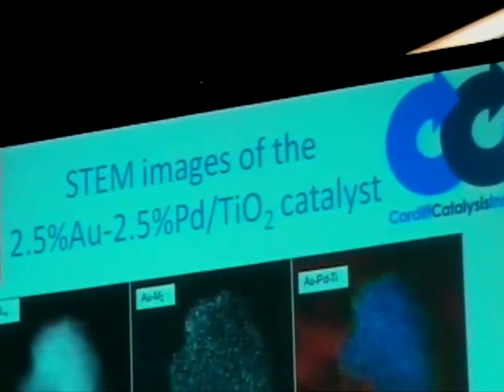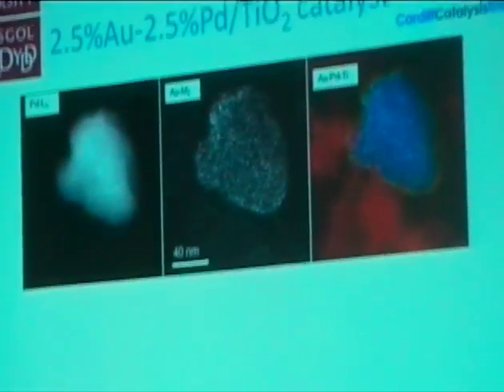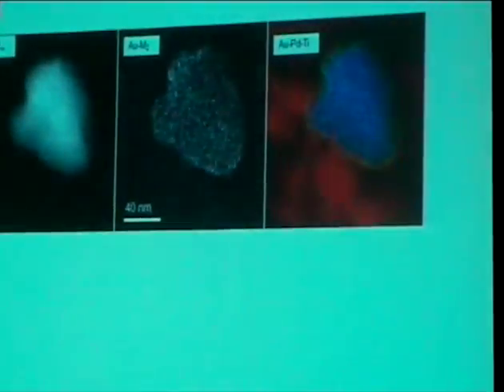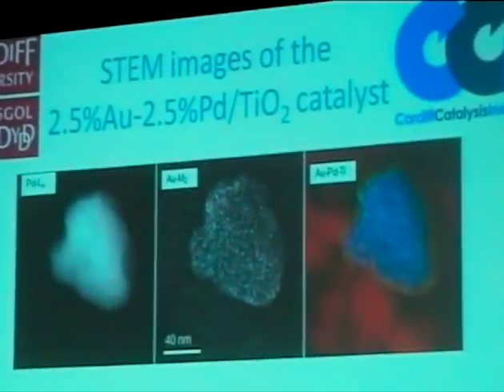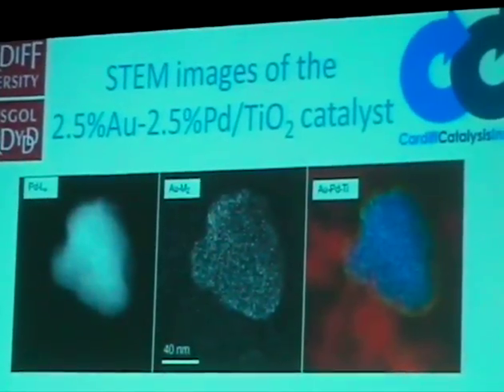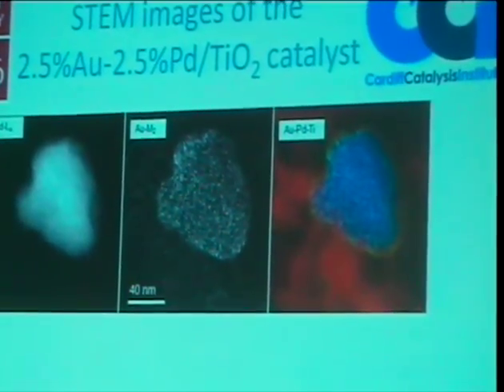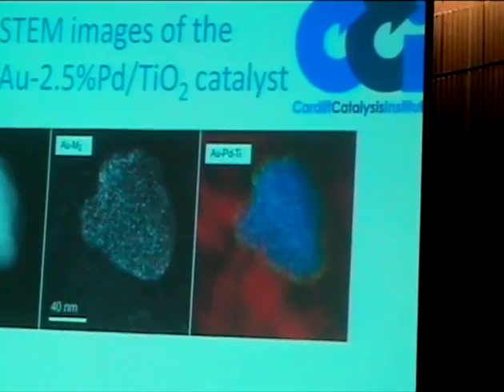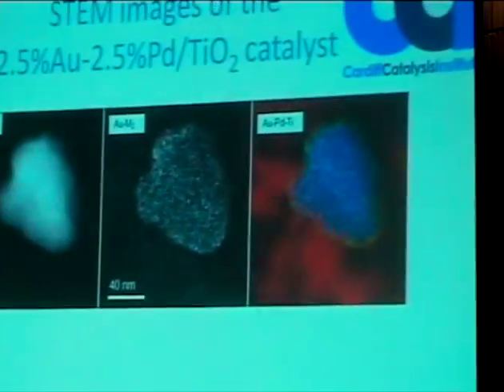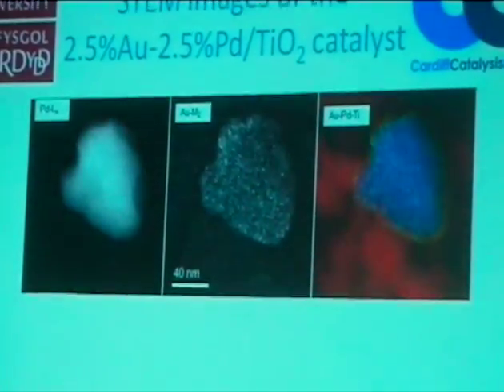If we take a closer look at the structure of these gold palladium alloys after the oxidative high temperature treatment, we can see that they're not homogeneous alloys. After just the drying step, we do observe homogeneous alloys, but these catalysts are very unstable in the aqueous conditions during the reactions. To impart stability into these catalysts, we need the high temperature heat treatment. During this heat treatment, we can see an evolution in the structure of the gold-palladium nanoparticles. What we see is that the gold is in the core of the particle, and the outer shell is made of palladium. So these catalysts can be used very effectively for hydrogen peroxide synthesis.